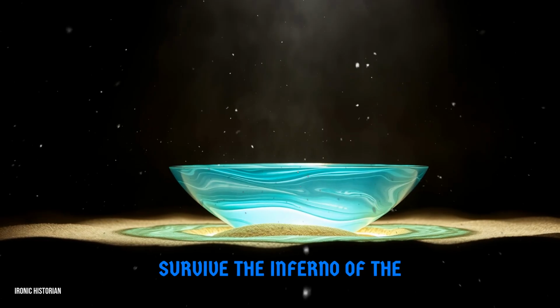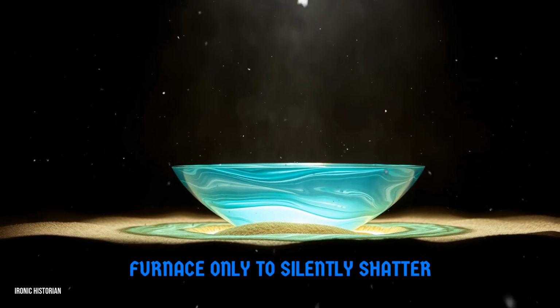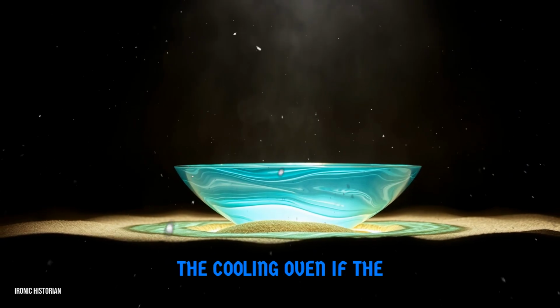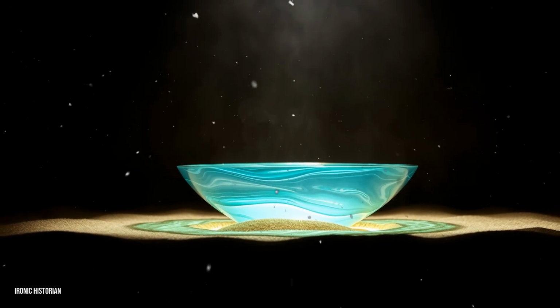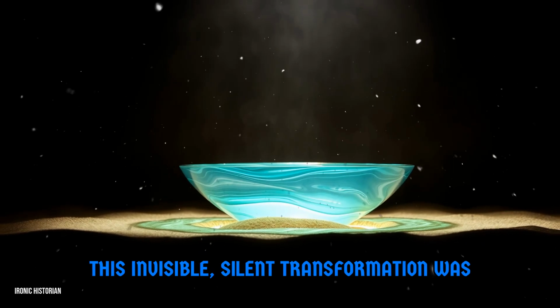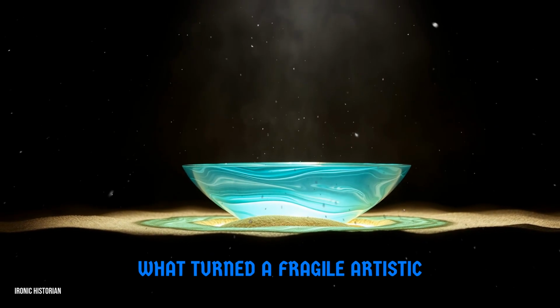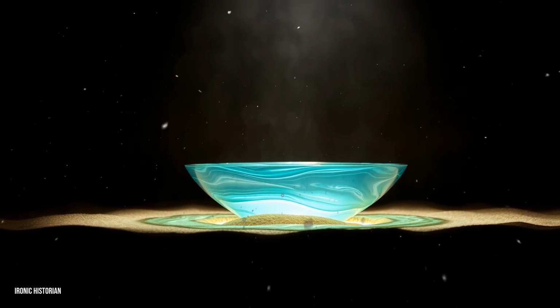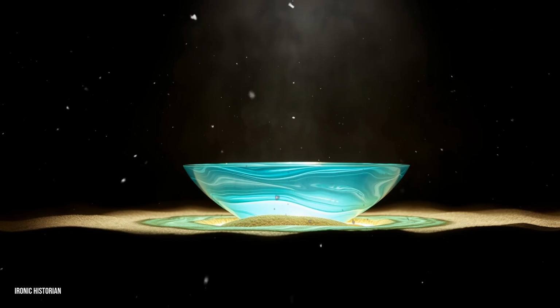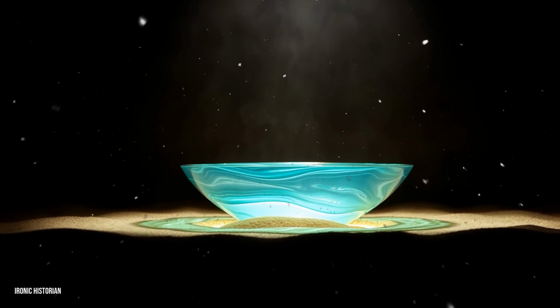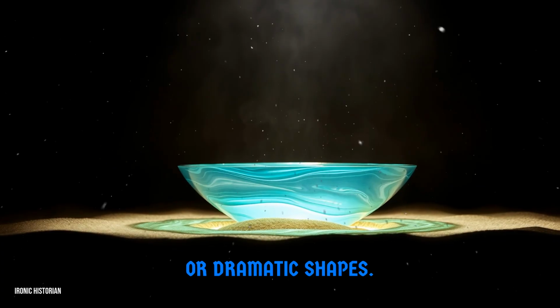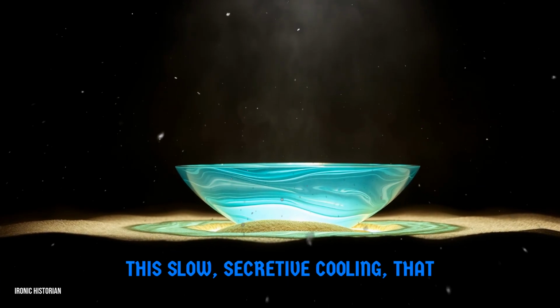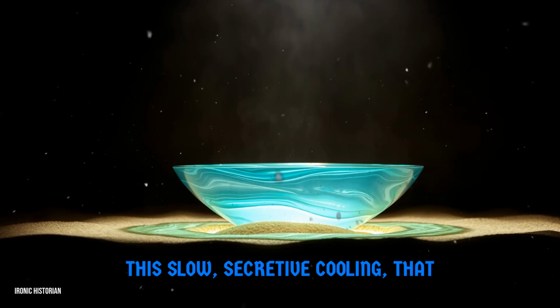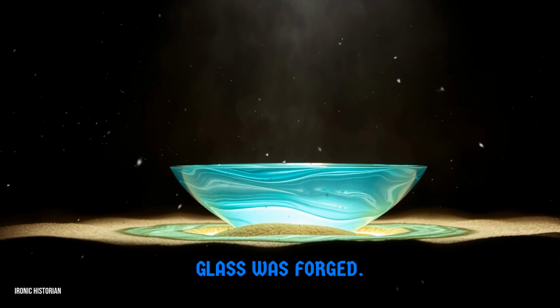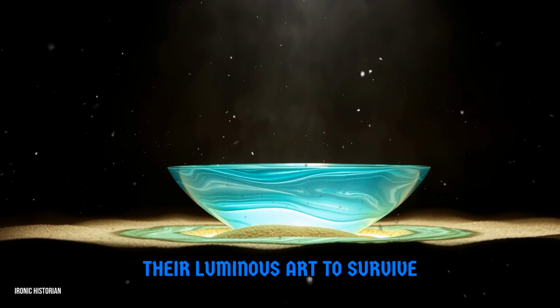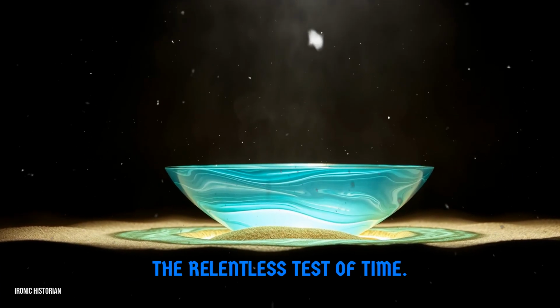A batch of glass could survive the inferno of the furnace, only to silently shatter in the quiet dark of the cooling oven if the annealing curve was wrong. This invisible, silent transformation was what turned a fragile artistic expression into a durable object meant to last for centuries. The annealing lehr held no glory. It produced no brilliant colors or dramatic shapes. Yet it was here, in this slow, secretive cooling, that the true strength of medieval glass was forged, a hidden discipline that allowed their luminous art to survive the relentless test of time.